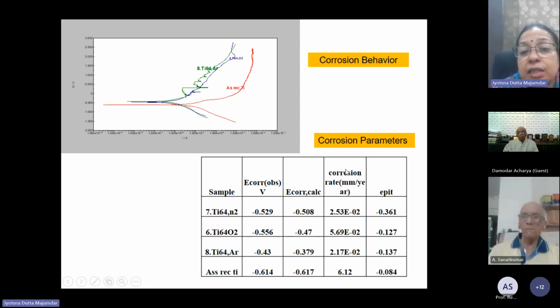The first error is that this is not truly the textured surface corrosion value or wear value. This is a combination of textured and non-textured surface. And the second problem is that while calculating the area, we just calculated the average area but not really the actual area because of the presence of the texturing. So these two corrections you have to make, and then do a little bit of calculation and find out what exactly the true wear and corrosion rate of the textured surface is.